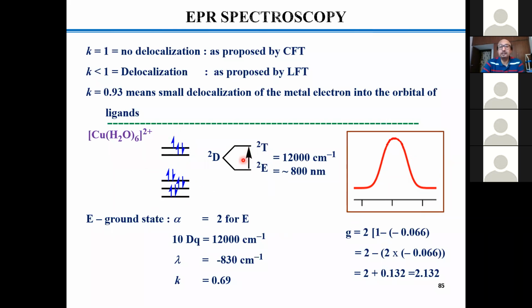And if you look at this absorption, which comes around 800 nanometer roughly, in centimeter units about 12,000 centimeter inverse, your lambda. Then if you put all the values, and it is an E term, so alpha equals 2 for E, 10 DQ known, lambda known, K is 0.69 considering the g. The experimentally observed g is 2.13, and your K is 0.69.